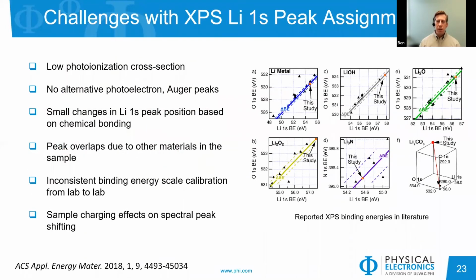Now, in general, one thing that is somewhat challenging with XPS of these materials is assigning the proper chemical states to lithium. Lithium is a tricky one in that it has a low photoionization cross-section, so the signal strength is quite low compared to other components that are typically in these samples. It only has one peak position, the lithium 1s. There are no other photoelectron peaks, no Auger peaks, so you're essentially trying to characterize it based on one peak position. And the peak shifts are not very large relative to maybe some other materials as you go from metals to oxides. And it is quite reactive in itself.